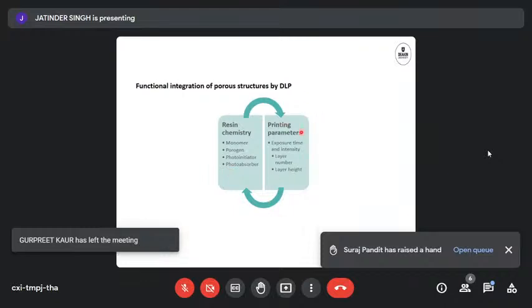Similarly, the printing parameters can be used to tune the porosity to your application, and we've played around with the layer number and layer height to get big pores for the chemotaxis studies, and we've used the exposure intensity using a grayscale mask to get in-print porous structures.